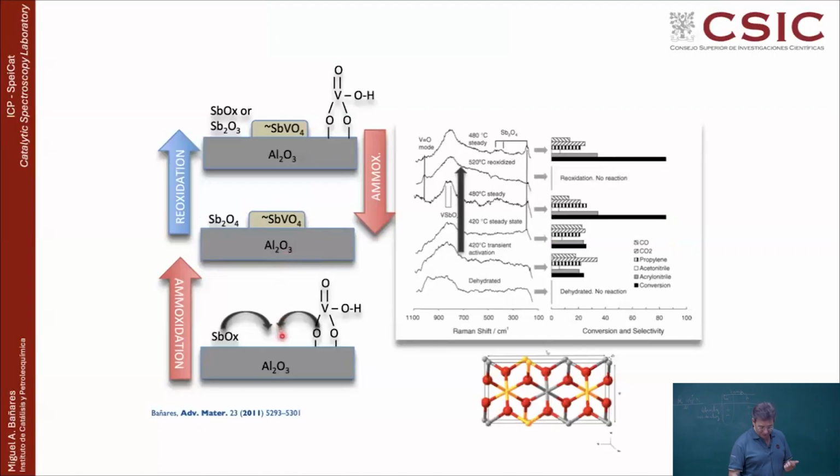reversible manner. Mainly, you have the fresh catalyst with dispersed vanadium and dispersed antimony. During reaction, you create this vanadium antimonate with segregated antimony phase. When we were reoxidizing, basically the dispersed antimony disappeared, which was SbOx amorphous phase, and you restore dispersed vanadium, and the vanadium antimonate essentially is there.